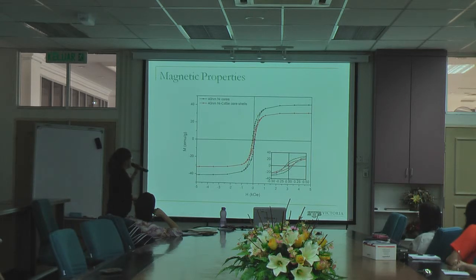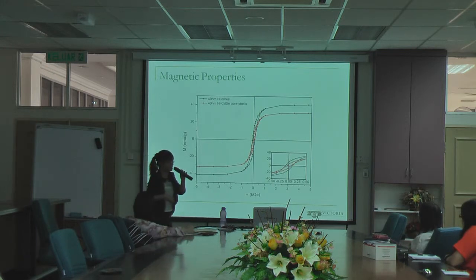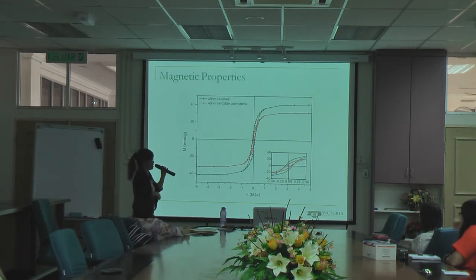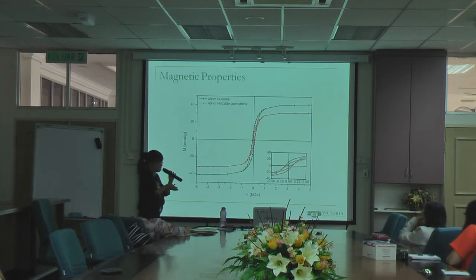This is quite understandable, and it's also been reported in previous works. That is because once the nickel particles have been coated with cadmium selenide, the overall magnetic content in the sample has also decreased. That's why we see an overall decrease of magnetic strength. And we also see a trend of the decrease of magnetic strength with the decrease of nickel nanoparticle size.